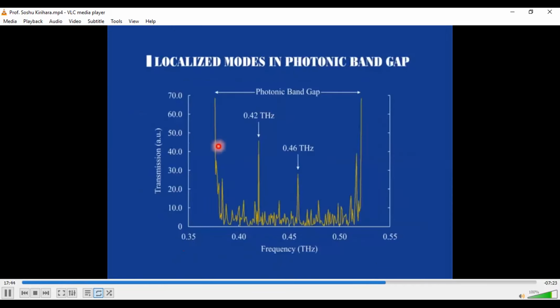This figure shows the measurement result. The photonic band gap opens due to the perfect photonic crystal structure, and the introduced structural defect creates a transmission peak of the localized mode at a specific frequency.